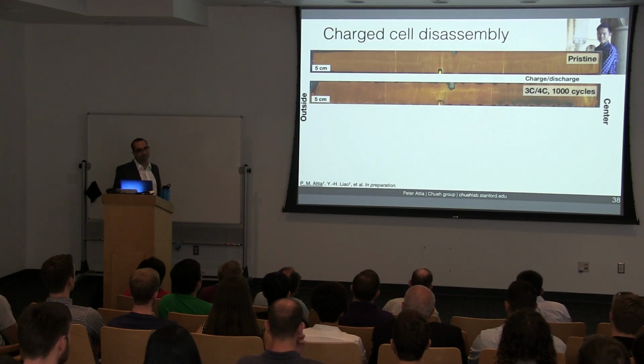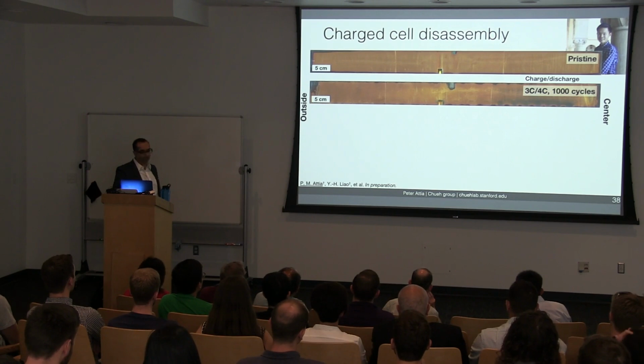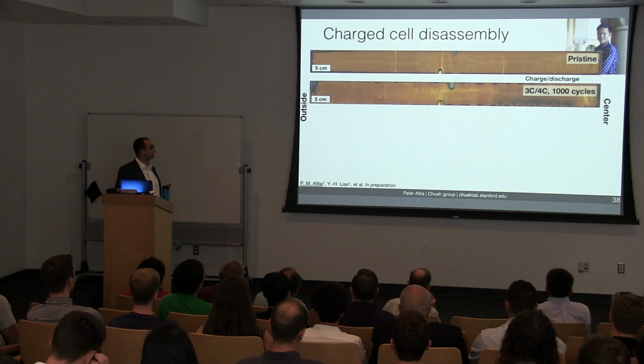If we look at one of the fast charge cells, like 3C, 4C, after 1,000 cycles, you see a bit of degradation on the right, but overall there's a lot of gold. That's consistent with the cycling results, where the cell seems to be lasting a while.